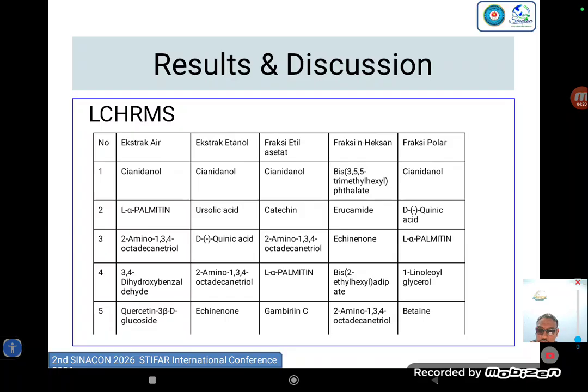Now we enter the results and discussion section. First, look at the compound profiling using LC-HRMS to understand exactly what is inside our extract and fractions. This table displays the top 5 compounds identified in each sample. A highly significant finding here is the presence of cyanidanol or catechin, a potential polyphenol compound. As you can see, it is the most dominant compound across almost all polar and semipolar samples, including water extract, ethanol extract, ethyl acetate fraction, and the polar fraction.